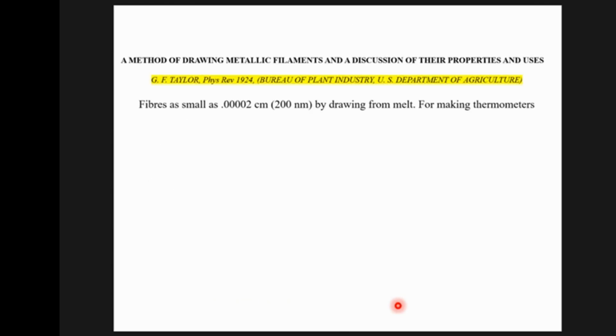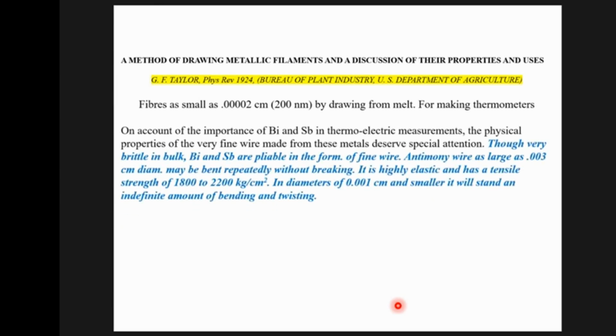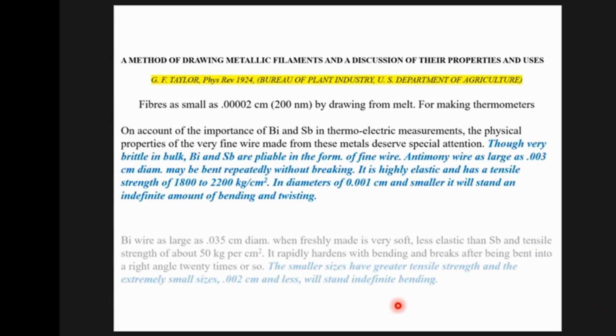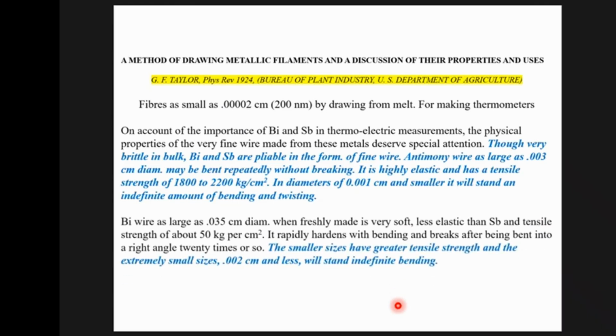About contemporary with Griffith was also this paper from the Bureau of Plant Industry, some very obscure institutions that did such work, where people were interested in thermoelectric wires, and these were for temperature measurements. These were experiments where very fine fibers of bismuth and antimony were drawn. And some of the things we now know very well were understood even then, namely that the strength increased and that the materials exhibited a fatigue limit. That is, below a certain stress, they would not fail at all, standing indefinite bending.